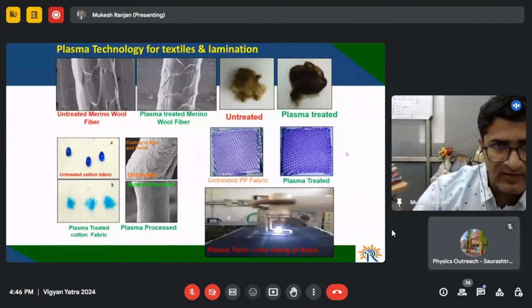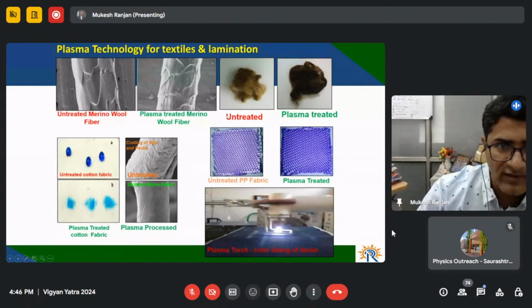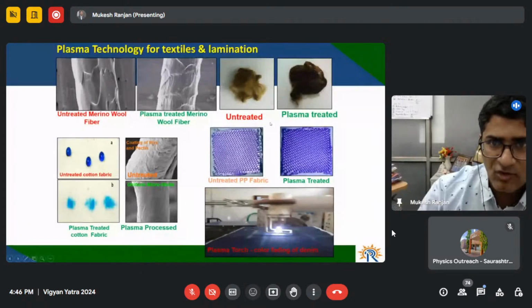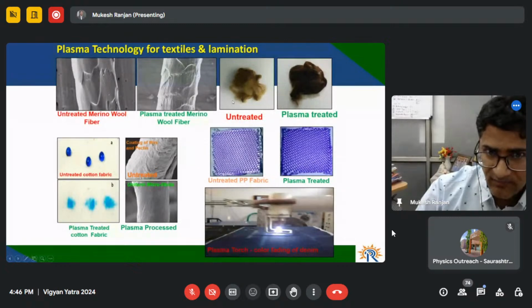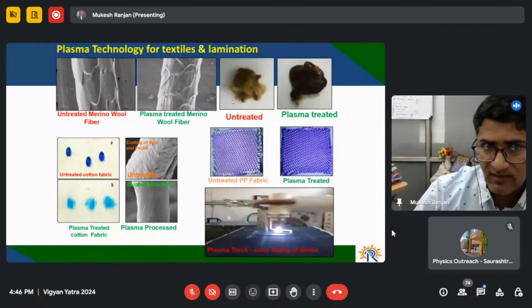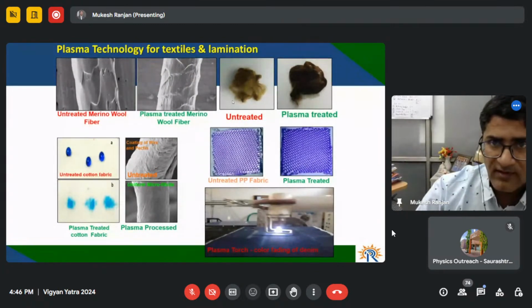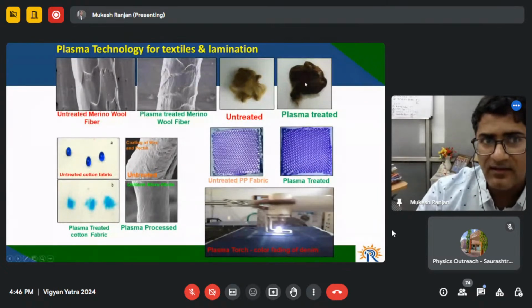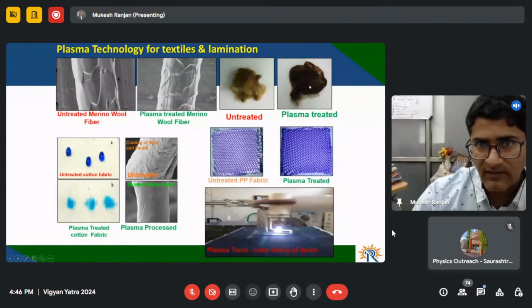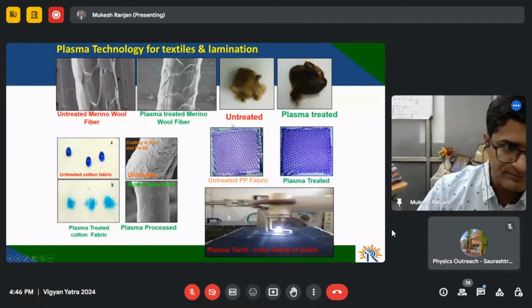So while they're burning the hairs, actually they are making your surface more reactive, basically it's a plasma only. So once you have a plasma treated here, you can see that the dye is absorbed much more as compared to the untreated one. So plasma actually basically makes your surface more active, and it removes the contamination from your surface, and that helps the dye molecules to spread more homogeneously on the surface and then deep inside. And then because the roughness is also increased, the surface area is increased, so the dye is actually absorbed much more as compared to the untreated sample.